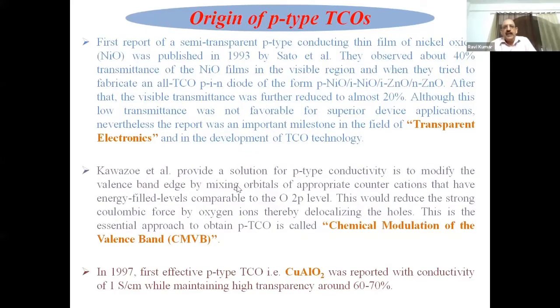And if you look at the literature and you start some kind of research, you start searching, so that if someone has done something, you may get some lead. When you go to the literature, we go back to 1993. Sato, a Japanese scientist, made a nickel oxide. They observed about 40% transmittance of the nickel oxide film in the visible region, and when they fabricated a p-i-n diode like p-type nickel oxide, insulating nickel oxide, insulating zinc oxide, n-type zinc oxide, they found that the transparency reduced to 20%.